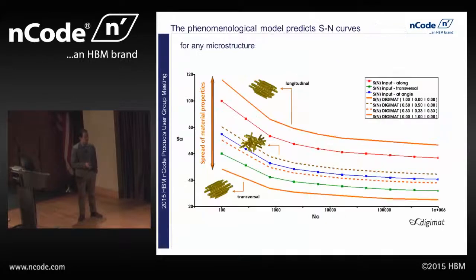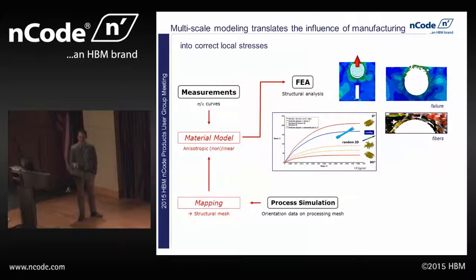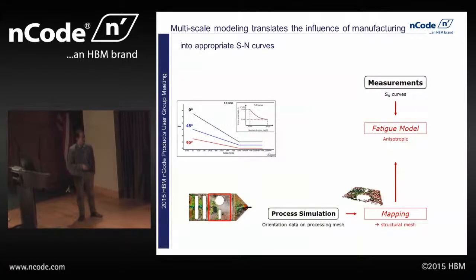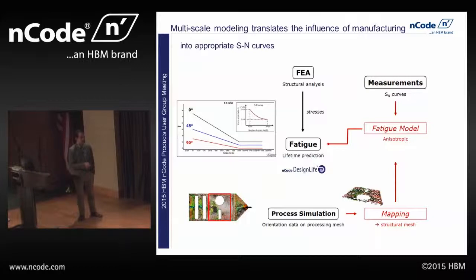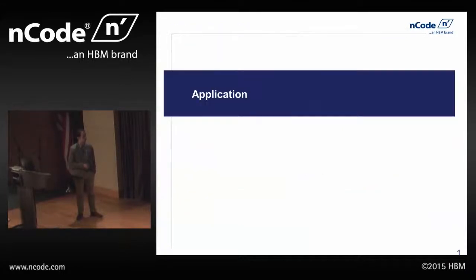So once we've got our damage model, then we need to take that and apply it at the part level. And we're going to use the same process that we did before to come up with our stress state. So we're going to take the information coming from our manufacturing simulation. We're going to bring that into our finite element analysis and use that linear elastic analysis to predict the stress state in our part. We're then going to use our SN curves to come up with our damage model. We're going to bring in those fiber orientations into nCode, as well as that stress state coming from our previous finite element analysis, and we're going to use that to do our part level lifetime prediction for our component.